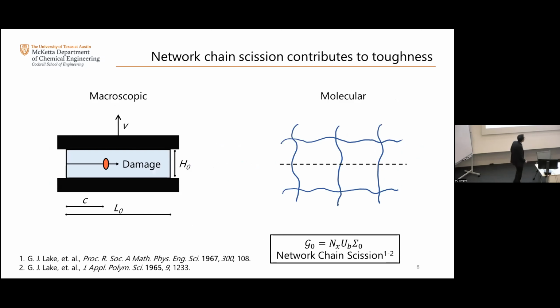And what we know is that even if you apply a deformation that is very low away from the crack tip, you have a stress concentration next to the crack tip. And the molecular picture that we have built since the late 1960s by Lake and Thomas that governs fracture is basically summarized in this schematic. The idea is, if you want to propagate a crack, the minimum that you have to do is break a monolayer of polymer chains.